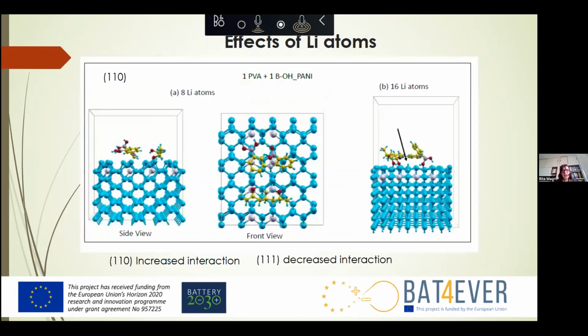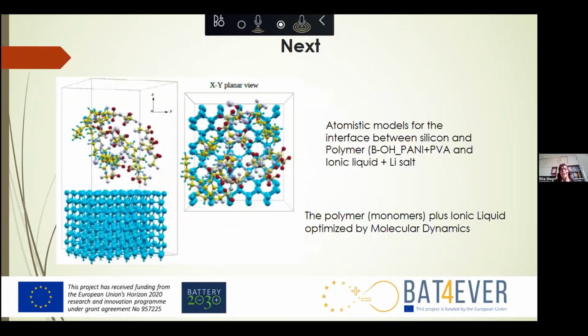So then we have also looked at what happens when we put lithium, and here something very curious happens on this kind of orientation. What happened is that the hydrogen detaches from the oxygen atoms in the boronic acid group and in PVA, and tends to attach, to passivate the silicon atoms in the surface, which is a very, very strange behavior. Next, we have optimized through molecular dynamics this monomer, and we have optimized the mixture of the self-healing binders plus ionic liquids and lithium salts. And now we want to study the interaction of the whole ensemble with the surfaces.